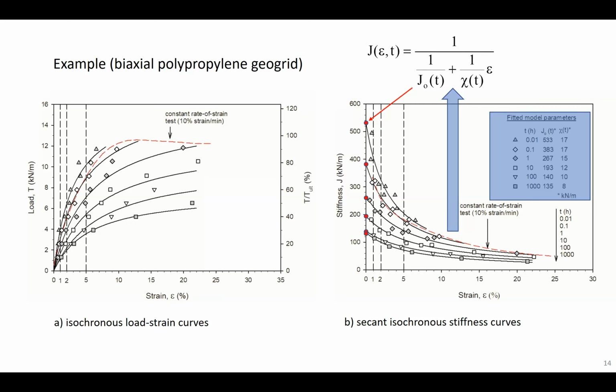And in the shaded box, you can see the numerical values for those two parameters. And it's interesting, you can see that as the strain in these curves increases, and time increases, these isochronous stiffness curves tend to converge as well. But when you're operating at very low strain levels and short times, you can see there's quite a big range of stiffness values that can be computed.